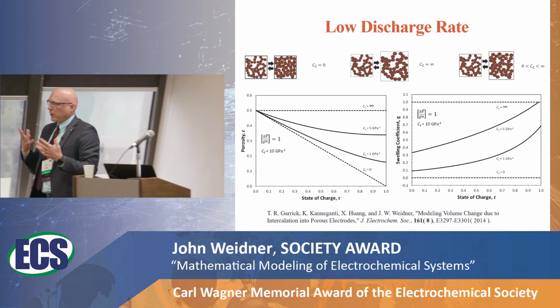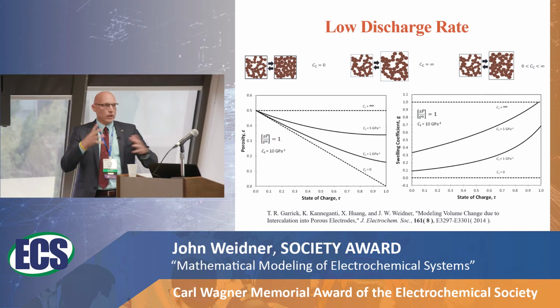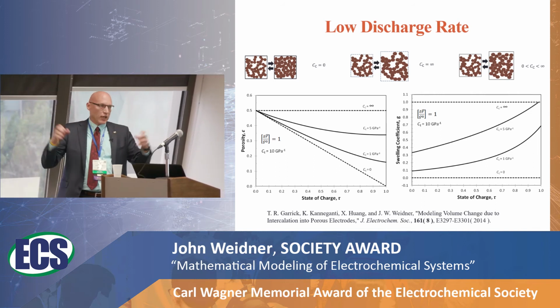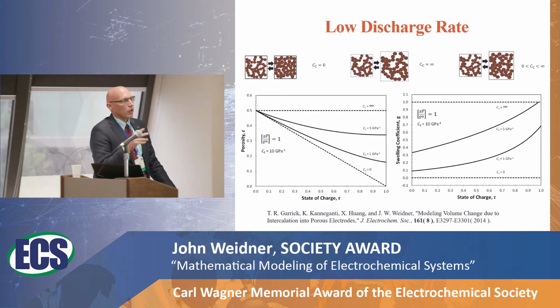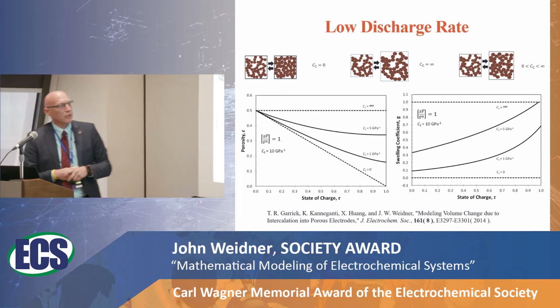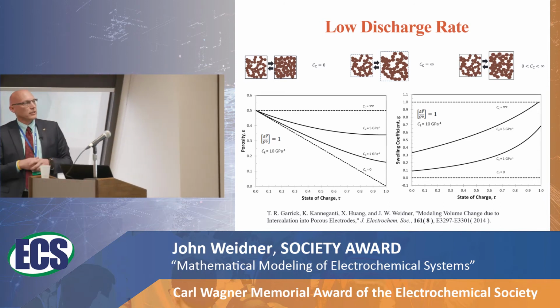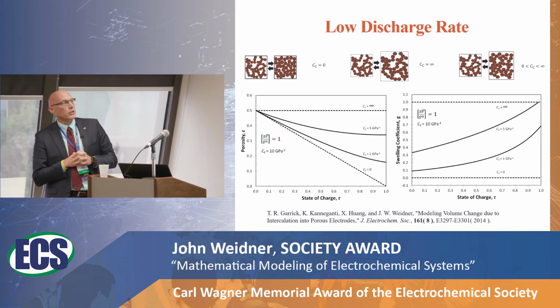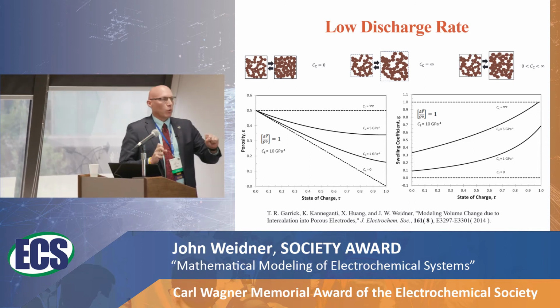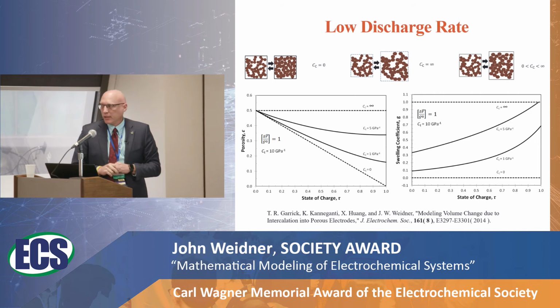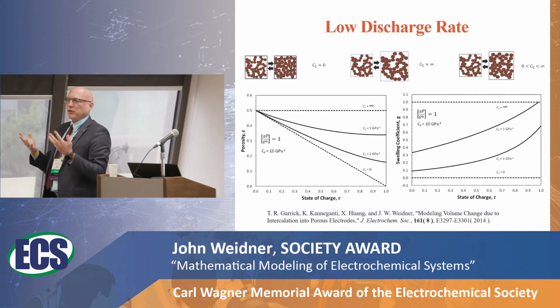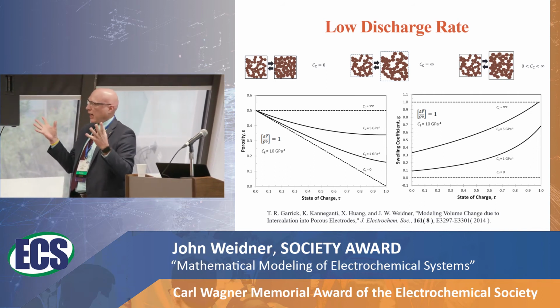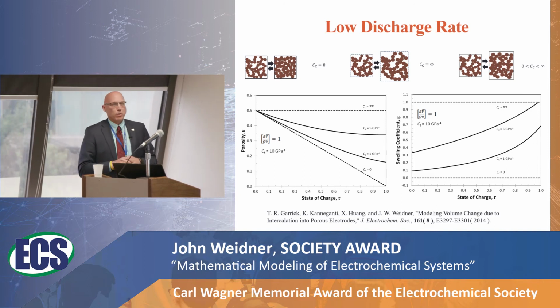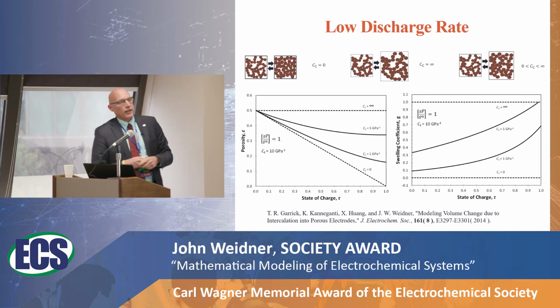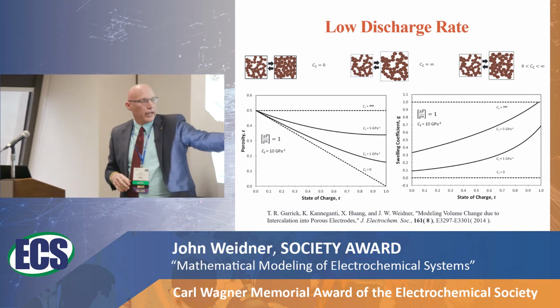And in a more realistic can, aluminum that is fairly rigid but not completely rigid, you will get a distribution. You will see the porosity is changing, but not linearly with time. And this swelling coefficient G, when we first did this, we just said that the G parameter is constant. Let's play with that. Here we see that the G parameter does change during discharge.